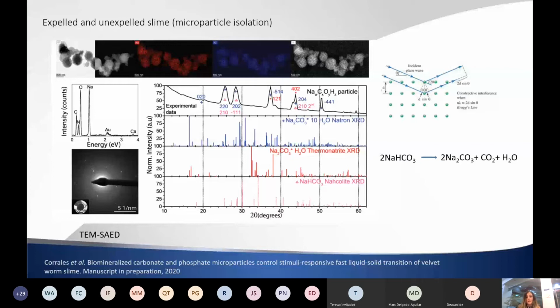So yeah, inorganic particles. We could also do a selected area diffraction. When you take the TEM, you select the area, as you see here in this corner, and you do diffraction there. With the diffraction, you can calculate the d-spacing, and with the compounds and elements you have, match which species are forming these particles. So we could detect two different ones, carbonates.